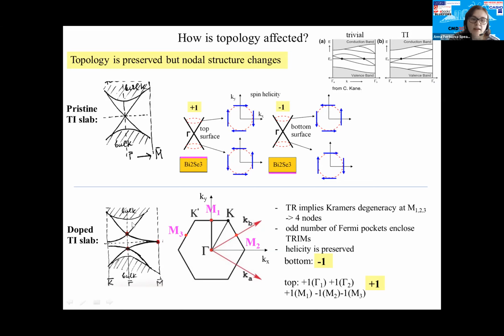Now, if we look at the schematic of the band structures that arise from our tight-binding calculations and also DFT, in the presence of the impurity resonance exactly at the Dirac point, we have this structure here with two split nodes and an additional node at the Brillouin zone edge. Still, if we put a Fermi level anywhere between the two time reversal invariant momenta, anywhere inside the bulk gap, you'll see that there is just one mode crossing the Fermi level.